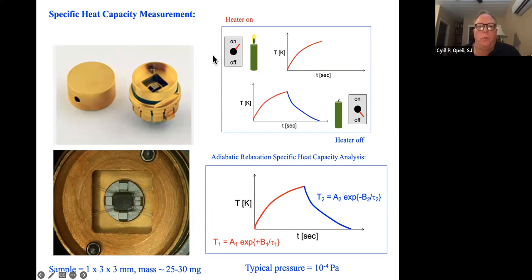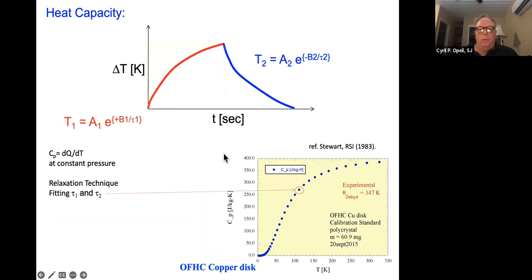Essentially, what you do for heat capacity is you heat something up, then you turn off the heat and let it cool down. So the heater is off in this fashion. If you know the timing and the temperature, you can use the adiabatic relaxation technique for specific heat analysis. You can determine the specific heat at a particular fixed temperature of the puck. From that, through some analysis, you can walk along, going down in temperature and up in temperature, as you can see here.